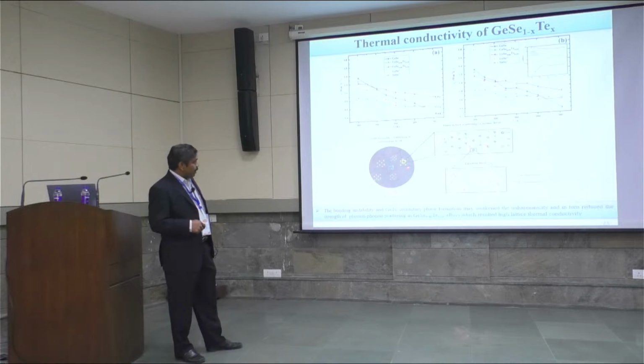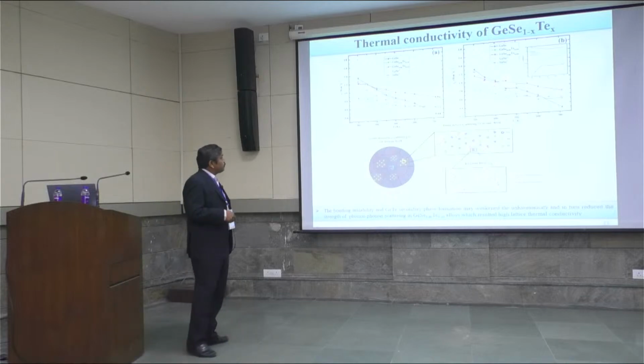So the scattering mechanism is the responsible factor for this kind of variation in the thermal conductivity. And the tellurium substitution increases the anharmonicity of phonon vibration in the system. And because of that, the thermal conductivity varies in the tellurium substituted sample compared to the pure systems. And based on these variations, we just measured, again,